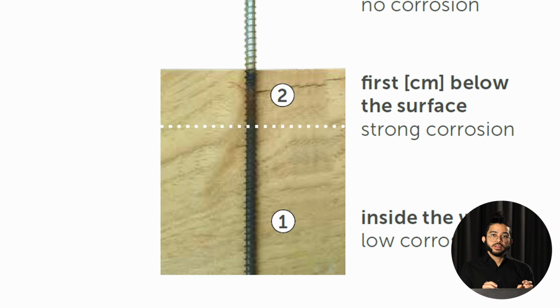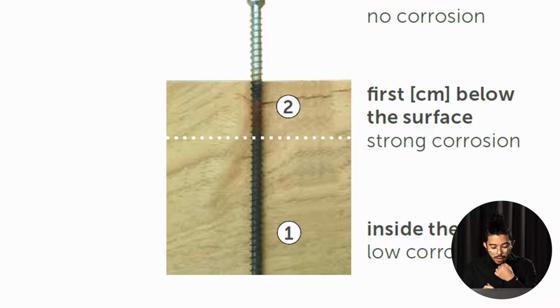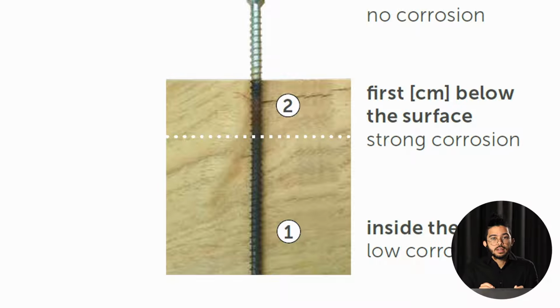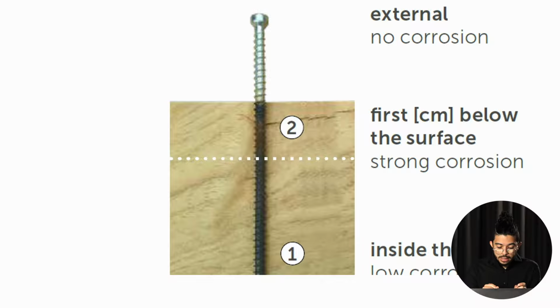What happens is that the tannins attach to the surface of the fastener and create a protective layer that increases the corrosion resistance of fasteners. But in the area with the number 2, water can wash down the tannins. When it rains, water can penetrate more or less until the white dots, washing the tannins and then allowing corrosion to increase.